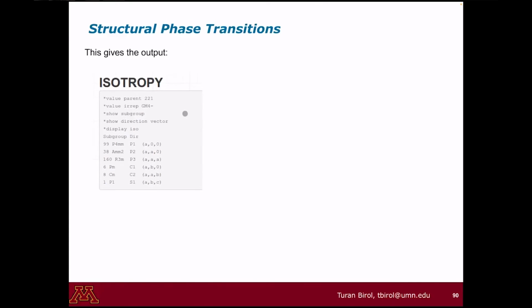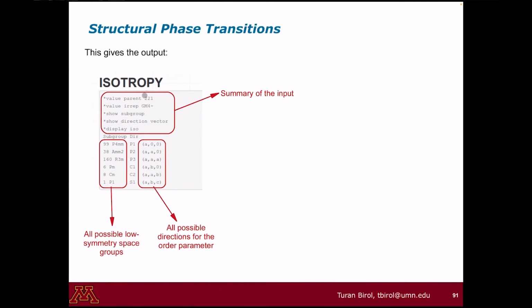Here I did not understand this order parameter, A, B. So this order parameter here doesn't know about titanium or barium, right? The input I gave is only within this box. This just says that I have some structure with symmetry 221. It doesn't even know that it's a perovskite. And then it says that the order parameter is gamma 4 minus because the phonon mode under question was a gamma 4 minus phonon, that you saw from the negative frequency in principle.